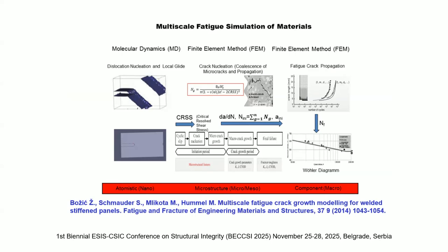Basically, fatigue is a multi-scale phenomenon. So we can assess some parameters like critical resolved shear stress on atomistic level and use them on micro scale level as the input data to, for example, the Tanaka-Mura model and assess fatigue life to crack nucleation. And after these cracks become a little bigger, like 1 millimeter or longer, then we have a different way of propagation. Then we have long fatigue cracks, for which we use some power law models, for example, the Paris equation.